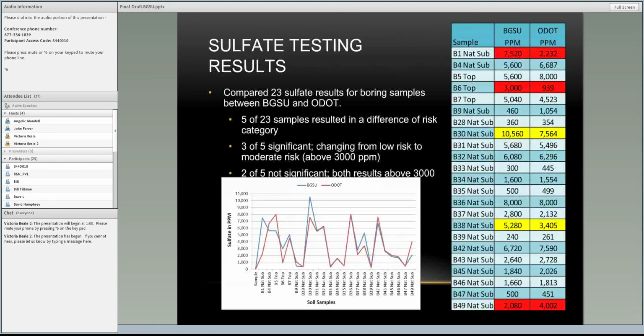So we looked at 28 boring samples, but we only had 23 samples where we actually had results that compared to ODOT. So we did a comparison of those 23 samples, and 5 of the 23 came back ending up in different risk categories, and that's what we're ultimately concerned with. It's really hard, even within your own lab, to get the same sulfate parts per million result every time you do the test. So what you're really hoping for is to get into the right risk category. And as you can see, we were pretty successful. Only 5 of the 23 times were we different. 3 of these times were significant, which resulted in a change from a low risk to a moderate risk category.